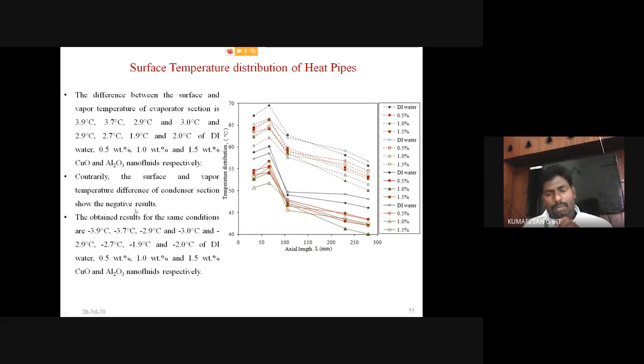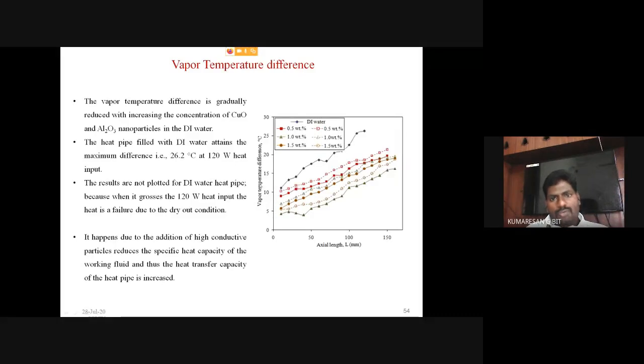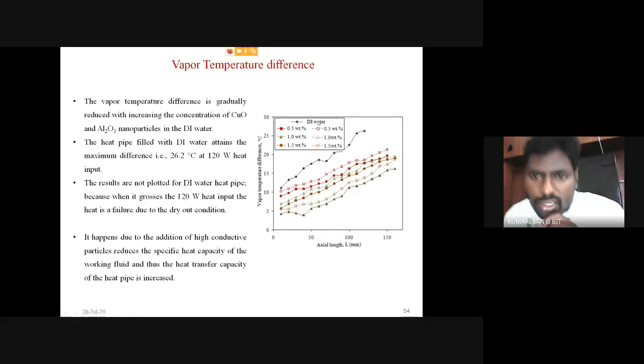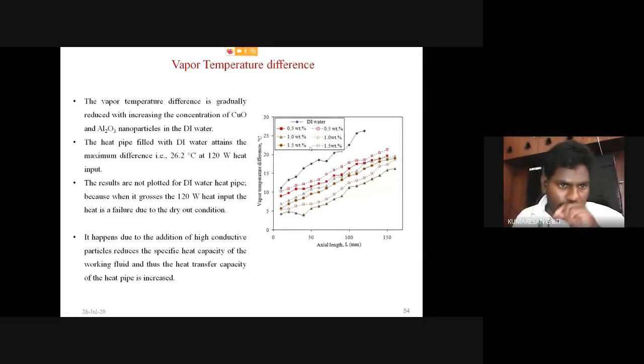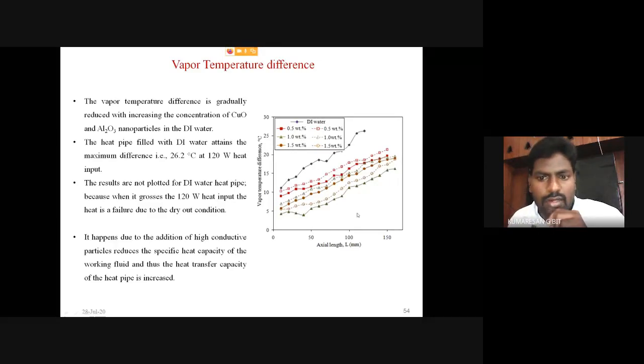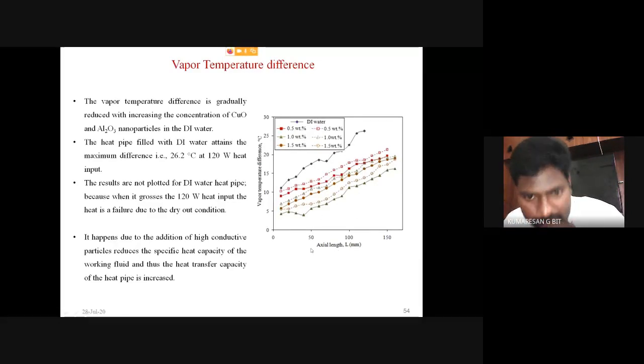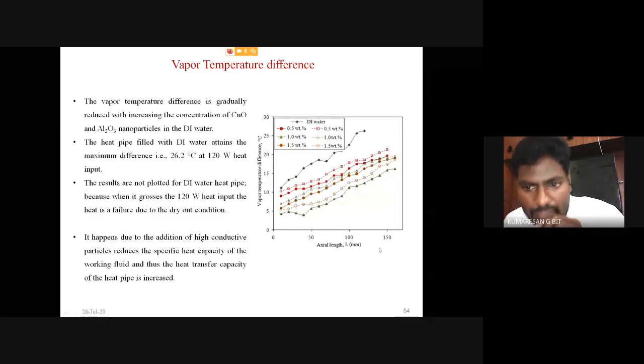This is because, as I have already explained, the circumferential heater has direct contact with the evaporator section instead of the condenser area. Then the vapor temperature difference is compared here. First, the DI water results are shown in the blue color line. Then for the 0.5, 1 and 1.5 of the aluminum and the CuO nanoparticles are shown here. However, irrespective of the nanofluid, the vapor temperature difference is gradually increasing with increasing axial length.